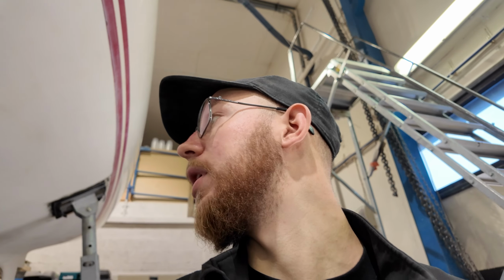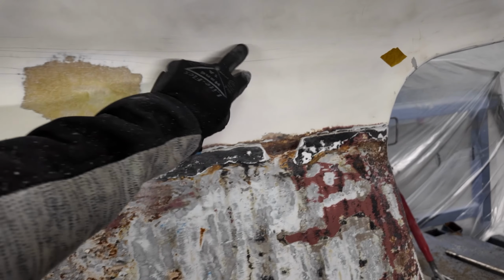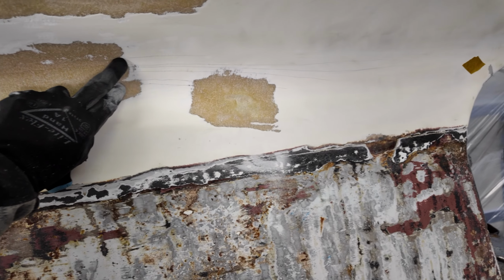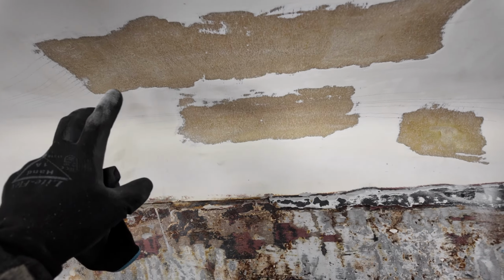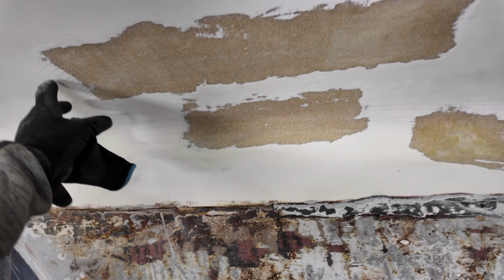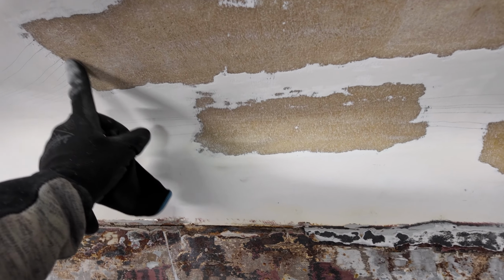Some of them might be actually from some kind of collision that happened to the boat at some point. The worst of them is probably this one that is right where the hull curves in near the keel. There is a bundle of long continuous cracks in the concave area and a series of spiderweb-like cracks right above it. I will open this area a bit more to have more surface for the new material to adhere to and just to make it a simpler shape to laminate.